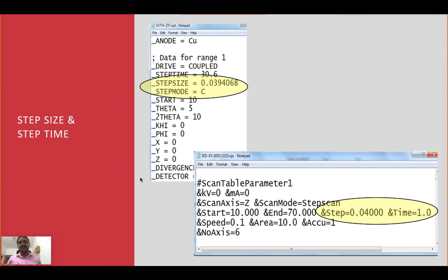It plays a major role in the statistics of your sample. For example, between 20 degrees and 21 degrees, if you are using a step size of 0.04, how many data points are available? We can calculate now. It is 20 to 21 divided by 0.04, you will get a number. That number will be for 1 degree. Then you can multiply it for 20 to 60 degrees, that is, people will take from 20 degrees to 60, then you multiply by 40. That's all. So this is the way the number of points increases.